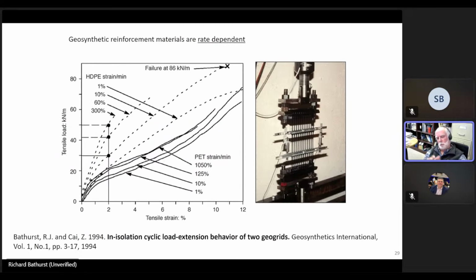So you can understand that by simply carrying out a tensile test using standard equipment like in the photograph on the right, and pulling on this specimen at different rates of displacement. And if you look at the dashed lines in this tensile load versus tensile strain plot, you can see quite clearly that tensile mechanical response is quite sensitive to rate. This is particularly true for polyolefin type reinforcement materials. It's less of a problem for polyester type.